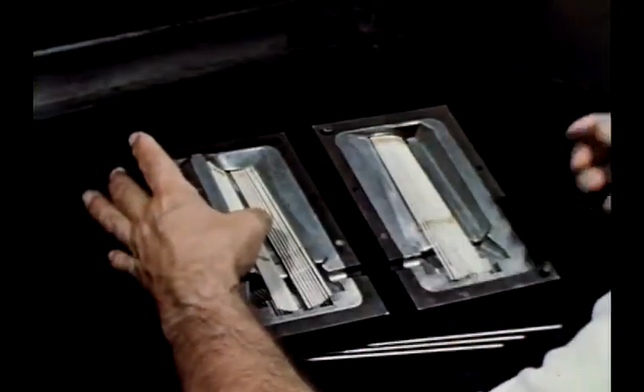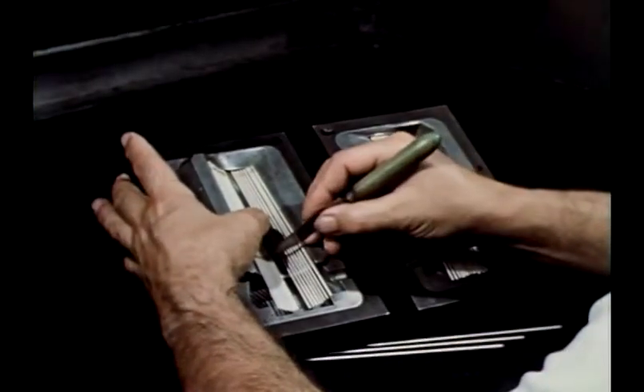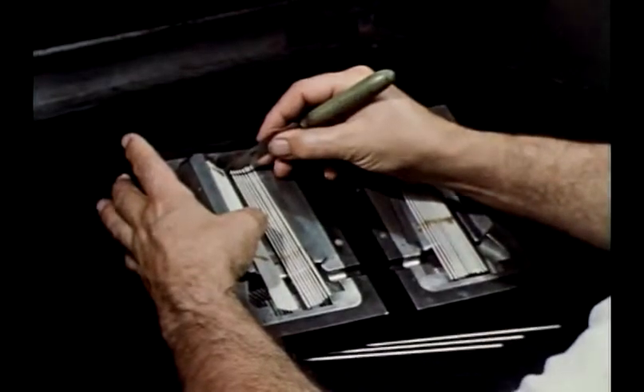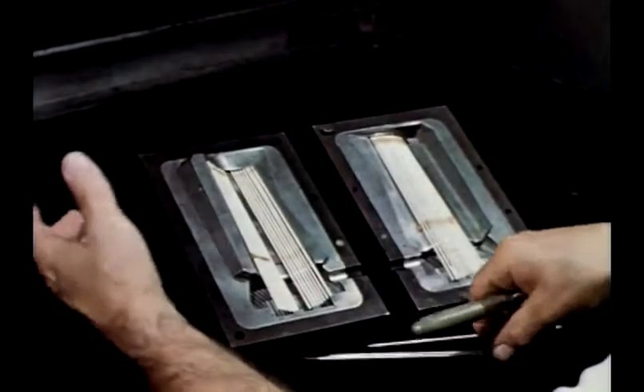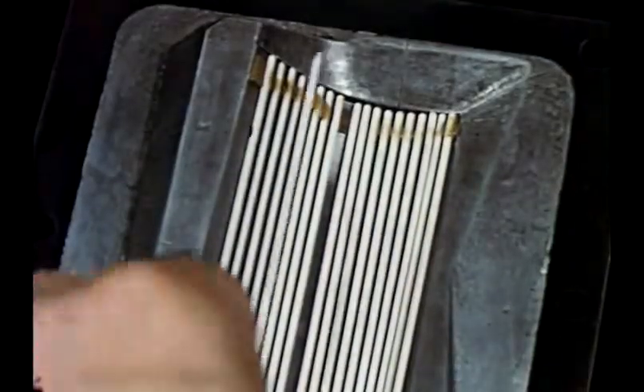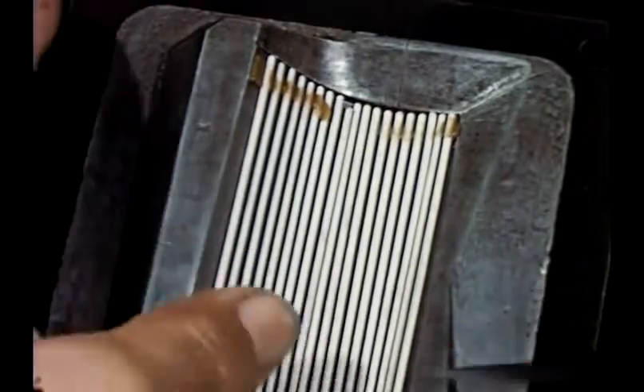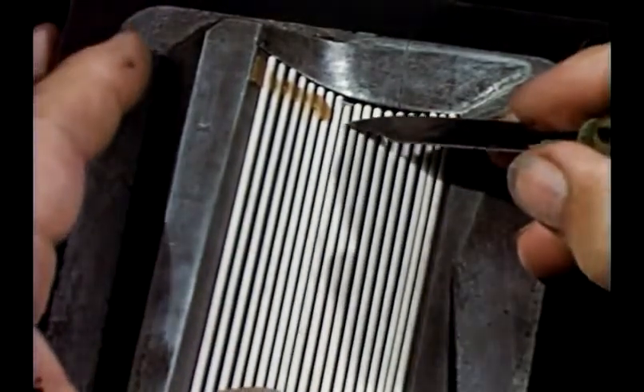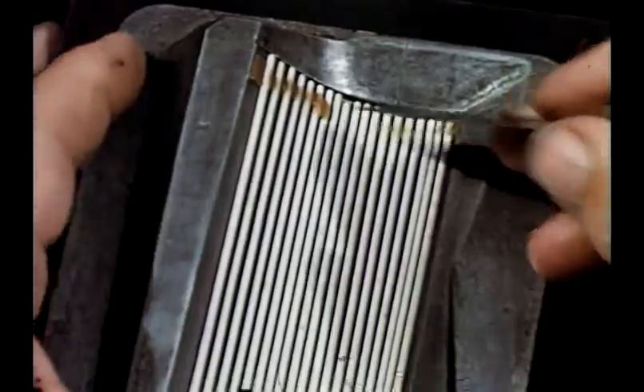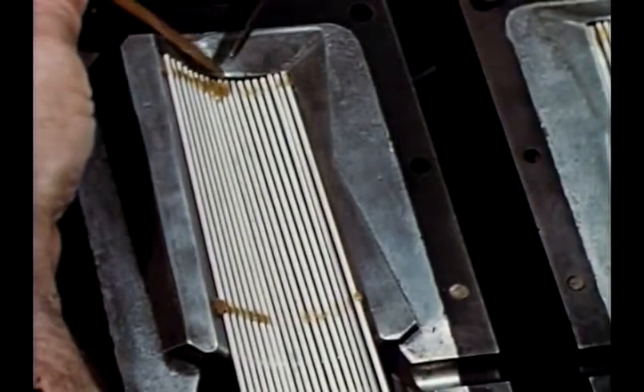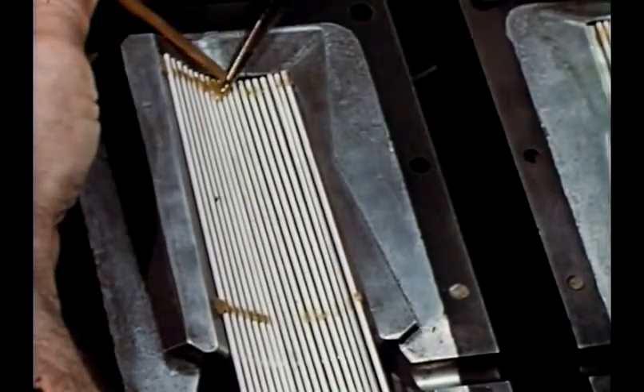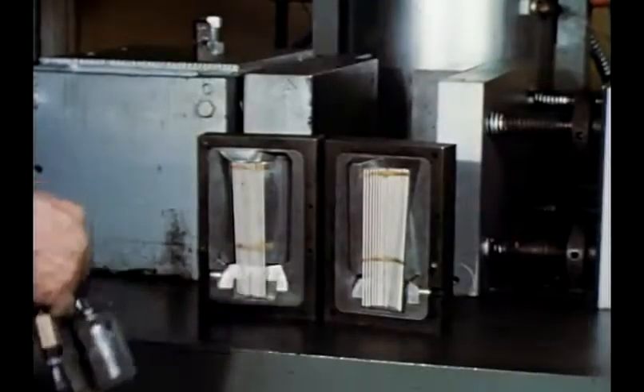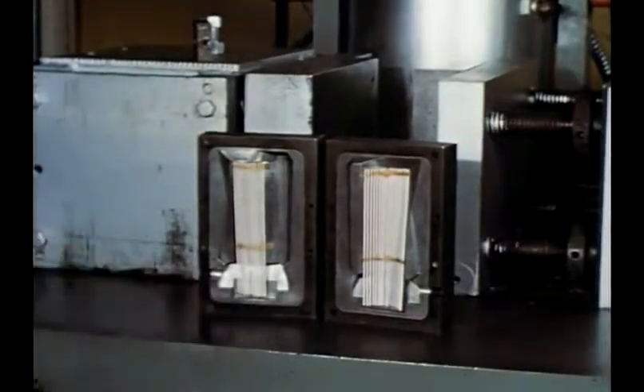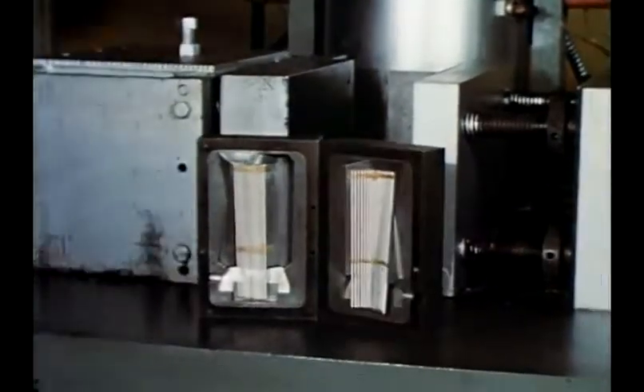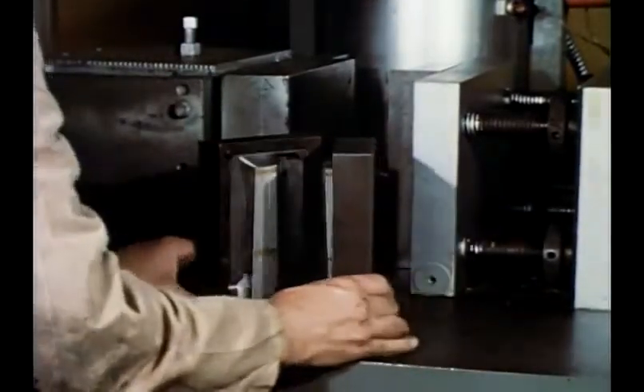Ceramic tubes are used as part of the casting mold to establish cores or holes through the turbine blade casting. Core tubes of the desired outside diameter are assembled in a pattern die. The core tubes are held in place by embedding them in a bar of soft wax using a hot wire or knife. The dies used are made of a low-melting alloy cast around a brass master pattern.